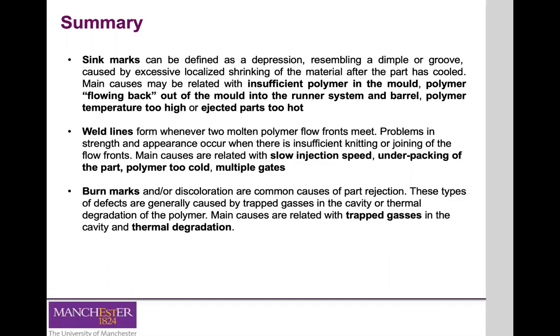The weld lines happen normally when you have multiple gates. And the most common reason is because we don't have enough temperature at these different front lines to allow for the blending of the materials and therefore avoid the formation of the weld lines. Burn marks are normally related with existence of trapped gases that can also be generated because the temperatures that we're using to melt the material are above the degradation temperature of your polymer.